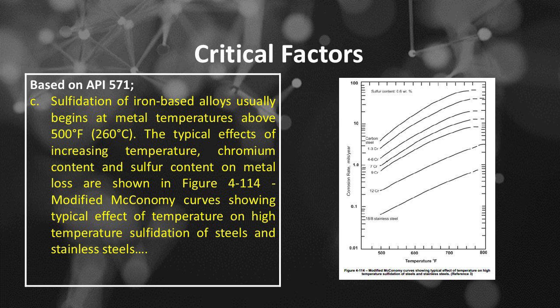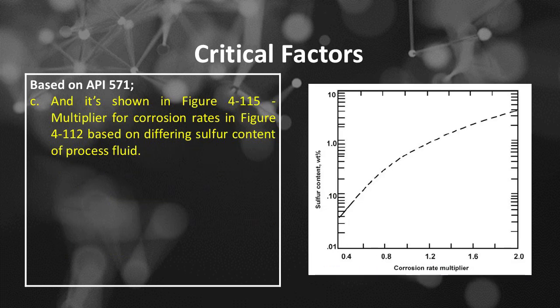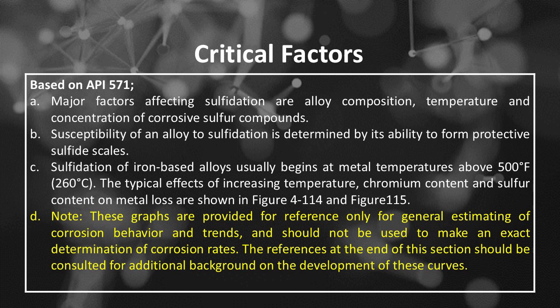The typical effects of increasing temperature, chromium content and sulfur content on metal loss are shown in Figure 4-114, modified McConomy curves showing typical effect of temperature on high-temperature sulfidation of steels and stainless steels. And it's shown in Figure 4-115, multiplier for corrosion rates in Figure 4-112 based on differing sulfur content of process fluid. Number D, note, these graphs are provided for reference only for general estimating of corrosion behavior and trends, and should not be used to make an exact determination of corrosion rates. The references at the end of this section should be consulted for additional background on the development of these curves.